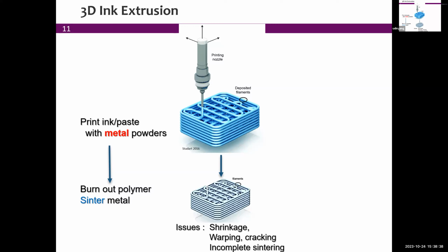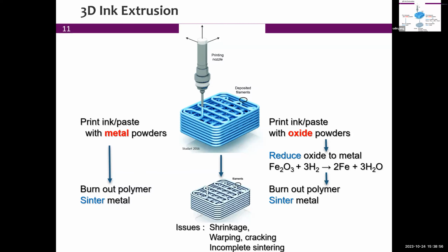The unavoidable issue is shrinkage. There's going to be shrinkage like anything that is sintered, but you also have to worry about warping, cracking, and or incomplete sintering, in particular if the shrinkage is anisotropic. So that's one thing that we were worried about when we started. What we are proposing is to actually do a bit of a roundabout. Instead of printing a metal powder that is in a paste here, we're actually going to print an oxide powder. A good example would be iron oxide. And the reason we do this is that we can reduce the oxide with hydrogen and form iron, and then burn out the polymer and sinter the metal.